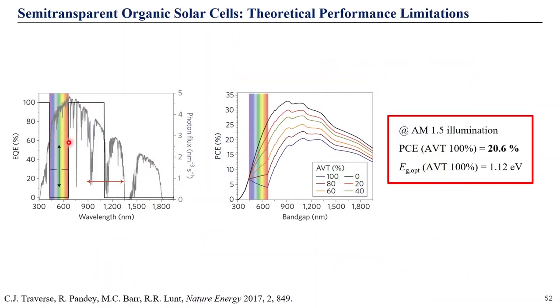Actually, the visible spectral range is quite narrow in comparison to the AM1.5 spectrum, and that's why even for AVT, average visible transmittance, of 100%, we get a theoretical performance, calculated based on the quasi-Shockley limit, of about 20%. As you see here, when we go for larger average visible transmittance, the optimal band gap is shifting towards lower values, and for AVT 100, we get an optimal band gap of 1.12 electron volts. So that is really great. However, in reality, we deal with AVTs of about 30% and performance below 10%. So that is really a challenge to overcome, and in order to do that, we need to understand more about the device physics of semi-transparent organic solar cells.